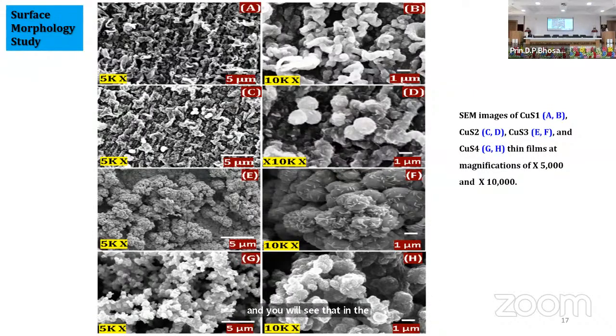Yeah, look at the morphology. The first one, of course, there are different magnifications. You will see that what is the change at the same magnification. If you go on increasing the temperature, you see that the morphology also changes. Now you see that the morphology is not looking good. It looks to be a little bit ugly. It's porous. And even at the high magnification, you can see some of the pores and the space in between the particles. Even though these are the nanostructure film, the agglomeration has taken place. So many small particles have come together and they have formed the bigger particles like this over the material. And you will see that all have the different morphologies.